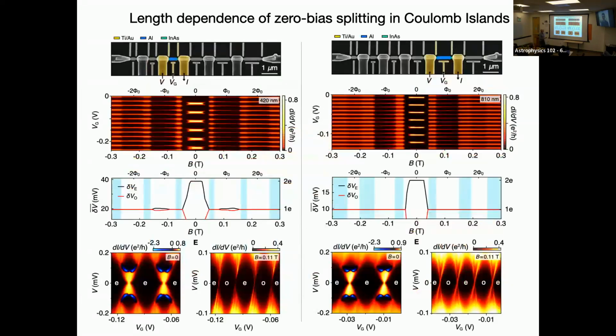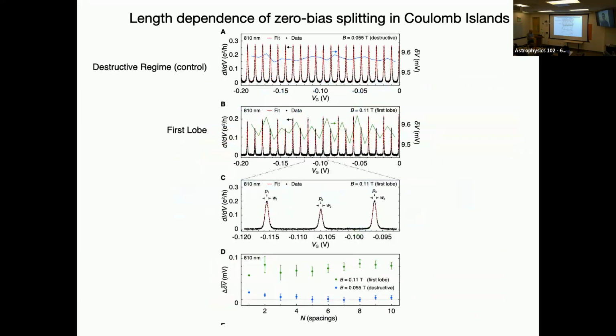So in order to do that, we just made a whole bunch of different lengths, short, medium, longer. And in each case, 2e, then equal spacing for destructive, then prison bars. And the prison bars got smaller and smaller and smaller until you couldn't even see them anymore. Until all of a sudden, the even-odd spacing was just gone. Now, if you were really careful and you really plotted out these Coulomb blockade peaks into hundreds of points over the peak, used some curve fitting to find where the positions were, really killed yourself, you'd still see that there was this remaining even-odd character.